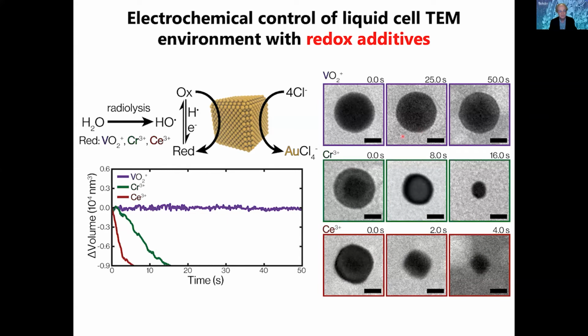If we go and look carefully at the redox potentials of these, they actually can make a great deal of sense because the cerium is the one that's at the highest oxidation potential, the chromium next, the vanadium the lowest. So it appears as though by adding this species, we have set the redox potential inside the liquid cell. It's going to turn out to be quite important for us to be able to do that.